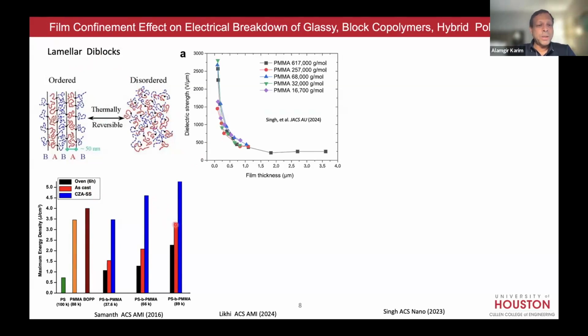Okay, all the red lines are different molecular weights in the disordered state. All you have to do is put it in a vacuum oven and heat it above its glass transition temperature, go up to say 160 C, hold it for a couple of hours, and it will go to the ordered state, which is microphase separated. And you will see that amazingly, the blue curve now is the annealed lamellar state. We apply the E field perpendicular to the lamellae, so the electrodes will be here and here.